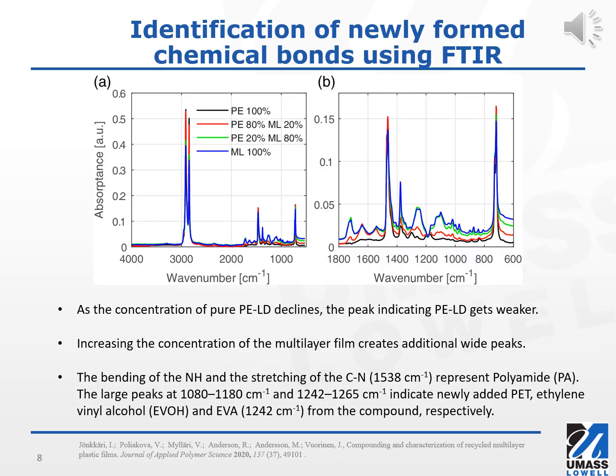So here you can see the Fourier transform infrared technique is basically used to illustrate newly formed chemical bonds. The peak that indicates LDPE becomes less prominent whenever there is a lower concentration of LDPE in its purest form. An increase in the concentration of the multilayer film results in the creation of additional broad peaks. Besides, the polyamide is represented by the bending of NH and the stretching of the CN bond at a frequency of 1538 per centimeter. This is representing polyamide, and large peaks seen at the 1080 to 1180 and 1242 to 1265 regions respectively suggest that the molecule has recently been added with PET, ethylene vinyl alcohol and ethylene vinyl acetate.